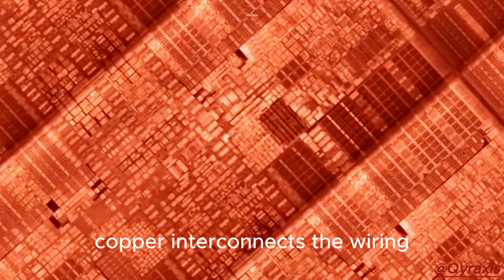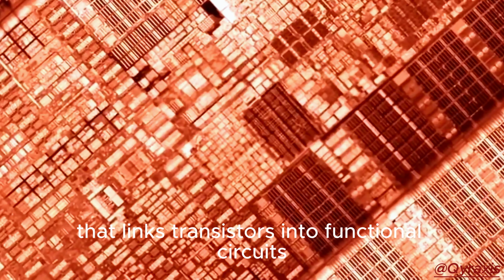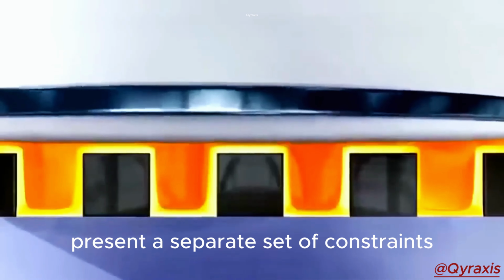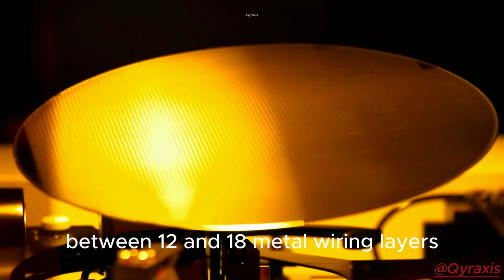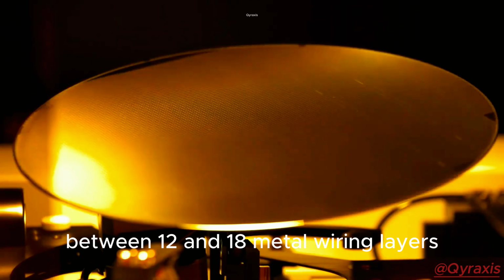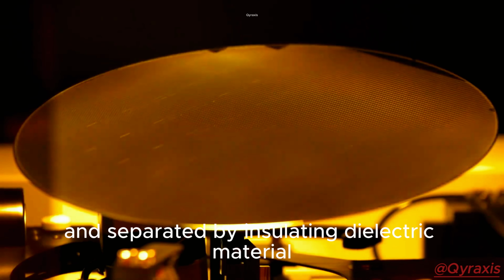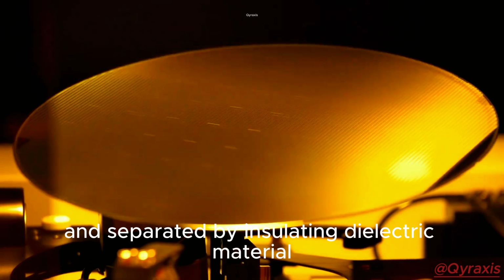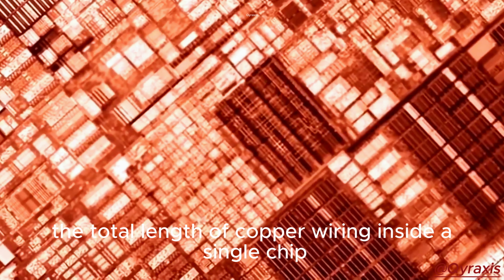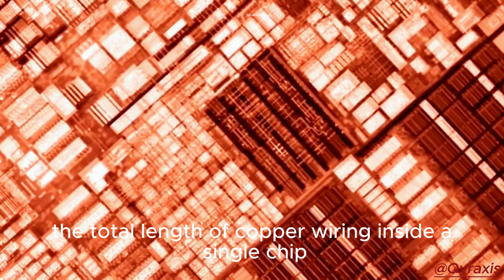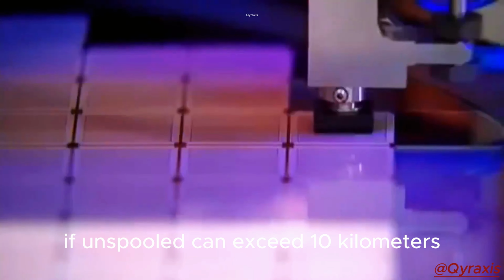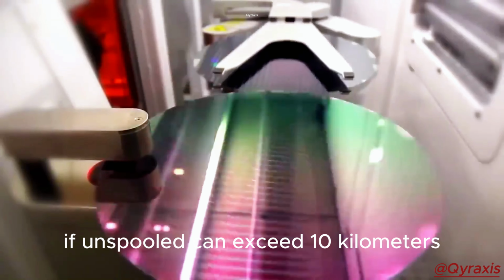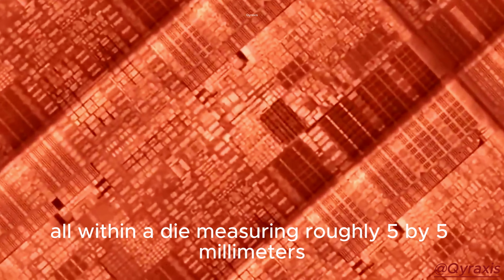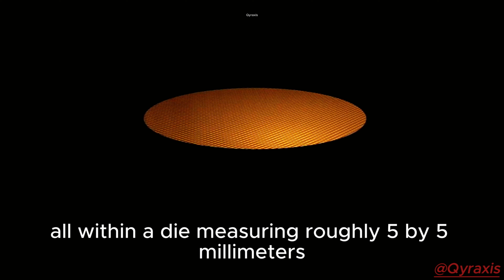Copper interconnects, the wiring that links transistors into functional circuits, present a separate set of constraints. A modern chip contains between 12 and 18 metal wiring layers, stacked vertically and separated by insulating dielectric material. The total length of copper wiring inside a single chip, if unspooled, can exceed 10 kilometers, 6.2 miles, all within a die measuring roughly 5 by 5 millimeters.